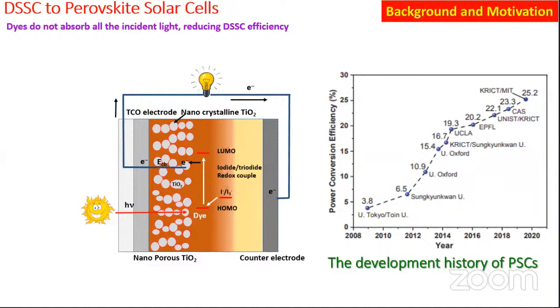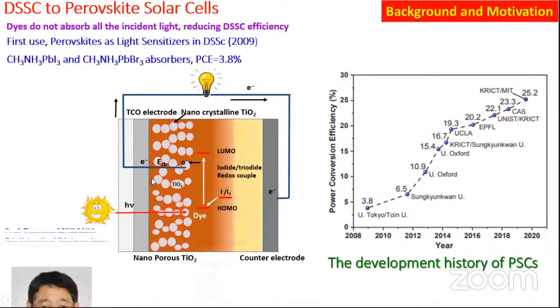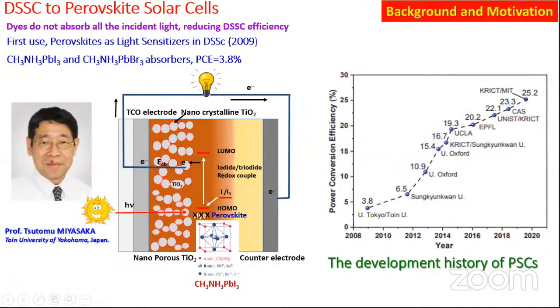In the DSSC, dye is the absorbing material, but the dye does not absorb all the light, and as a result the efficiency is lower. Miyasaka from Tokyo, Japan first replaced the dye with perovskite and achieved an efficiency of around 3.8%. The efficiency was improved to 6.5% by Nam-Gyu Park, a South Korean professor, by increasing the concentration of the perovskite. Then from Oxford University, they replaced the liquid electrolyte with a solid hole transport layer and achieved 10% efficiency. Then the efficiency increased from 10% to 25% by changing the mixed cation halide composition as well as surface passivation.